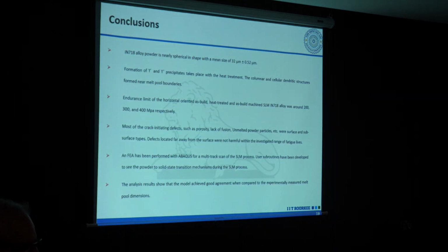And this is my conclusion. You see the powder is spherical with 30 micron size, and the formation of gamma double prime takes place with the heat treatment. Also, there is an improvement in the endurance fatigue limit with the heat treatment. The fourth point is that the crack has been initiated from defects of porosity and lack of fusion. And you see FEM has been performed with Abaqus for multi-track scan, and user subroutines have been developed to model the heat source as well as the user-defined field.